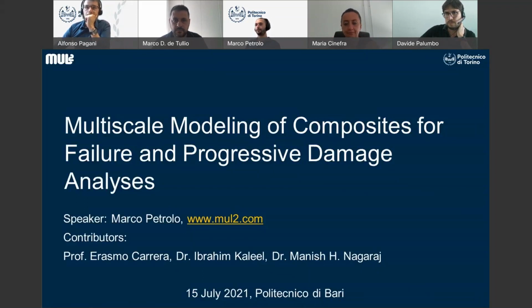Regarding fatigue, what I just said is that our main contribution is on the structural modeling. We don't do much into the damage model itself. So usually we use damage models that are available in literature. For instance, the results I showed you were obtained by using the CODAM2 model that is developed by the University of British Columbia in Canada. So from the material standpoint, we usually use what we find in literature. Given a good material model for fatigue or a numerical scheme to deal with fatigue, we are quite confident that we can insert our structural part in order to improve the detection capabilities with a decent computational cost, let's say.